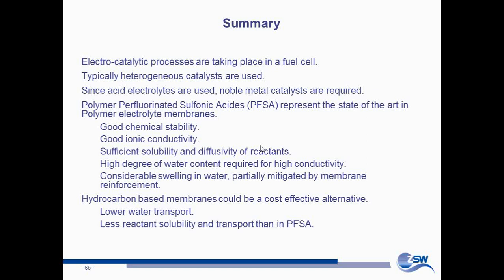So, in a sense, summarizing, we have electrocatalytic processes. They take place in the fuel cell at the surface of a catalyst. We are using heterogeneous catalysts. We are using acid electrolytes typically, and therefore we need noble metal catalysts. The perfluorinated sulfonic acids represent the state of the art. They have good mechanical stability, good chemical stability, good ionic conductivity, sufficient solubility and diffusivity of reactants.